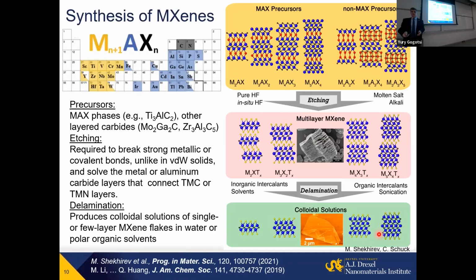Where does this name actually come from? There is a large family of layered ceramic materials, which is called MAX phases. You can look at them as layers of carbides or nitrides separated by monatomic layers of another element from this group, the A element from the blue one. So we have these transition metals possible, carbon, nitrogen, and these elements. What we did, following the work we did before on carbon materials, selective etching, we just etched, removed these elements. In fact, you can use also other layered carbides, nitrides, which are plentiful in other families, not related to MAX phases. But initially, we etched away A. What was left was M and X.